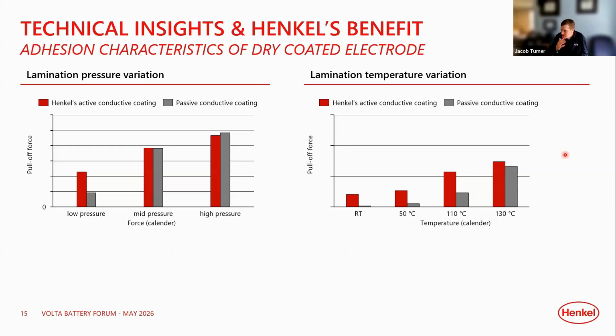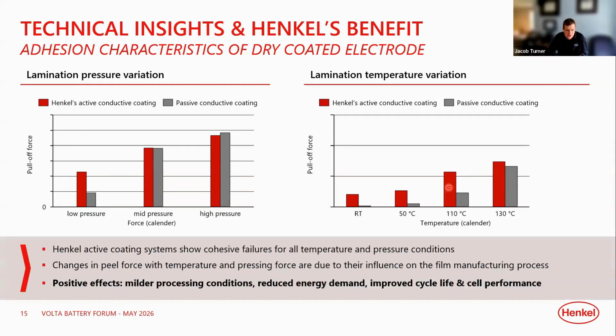You'll see on the next slide that the conductivity is still not quite as good, though. But where we really get the advantage is we start adhering even at room temperature with these materials, as long as adequate pressure is there. Typically, we would target something in this range, maybe 110 degrees Celsius, where this material is going to have that best lamination performance to really enable dry battery technology.